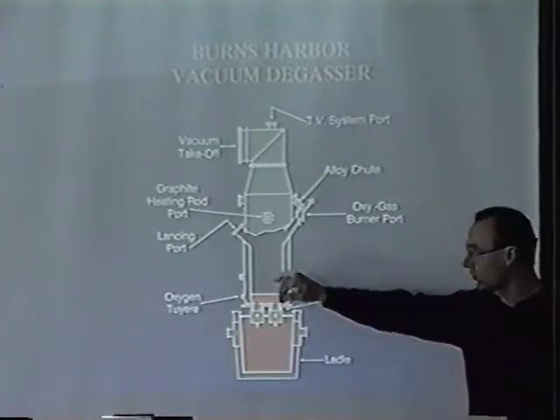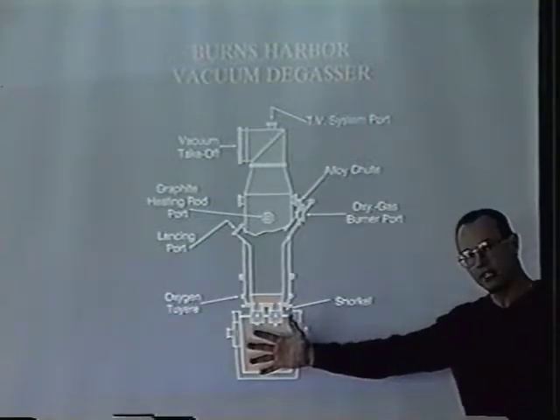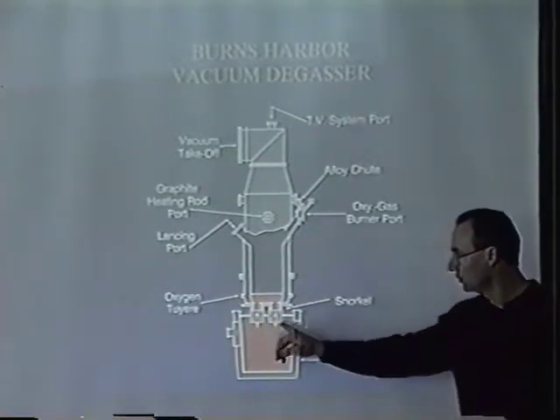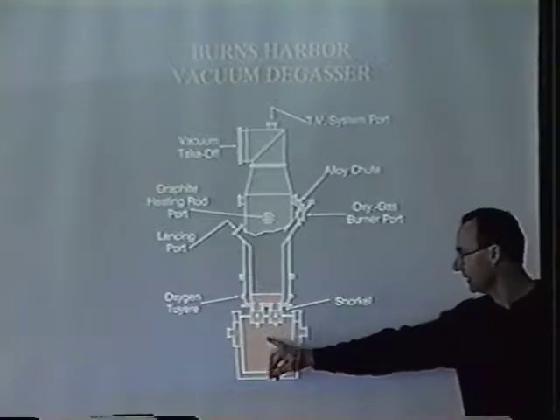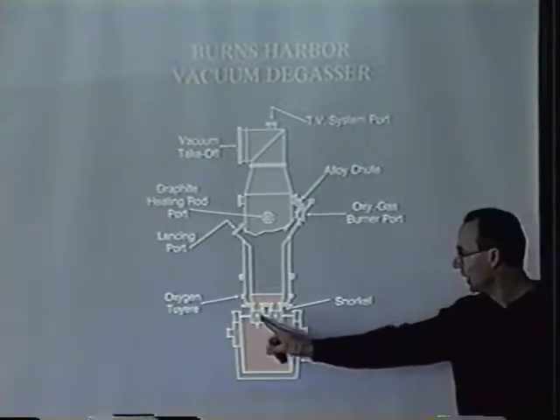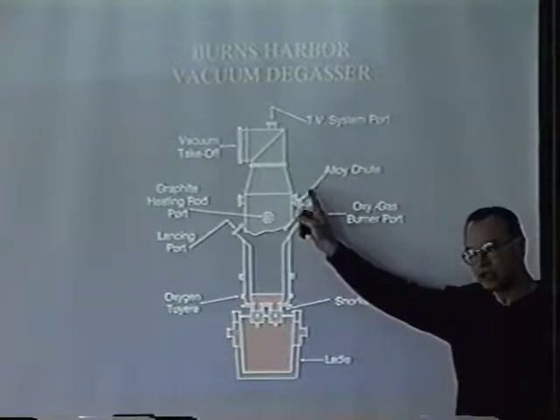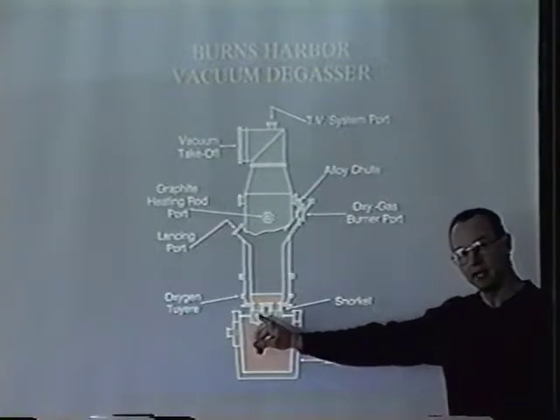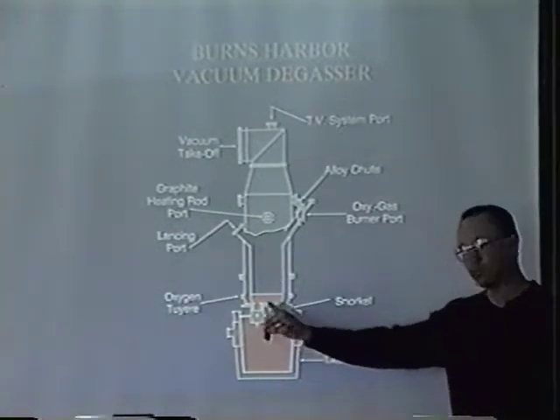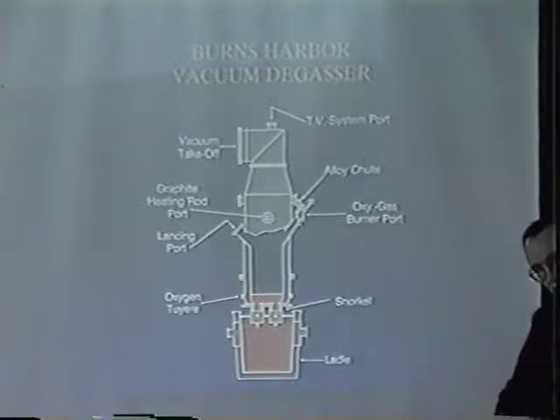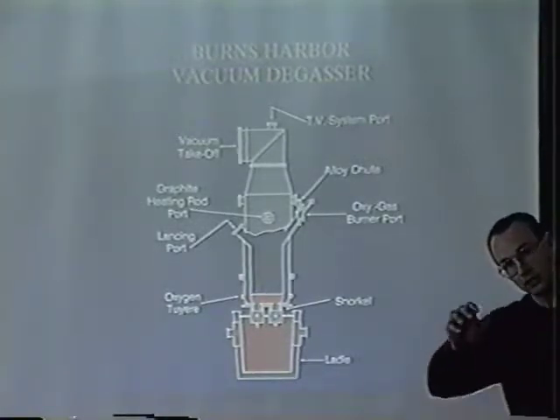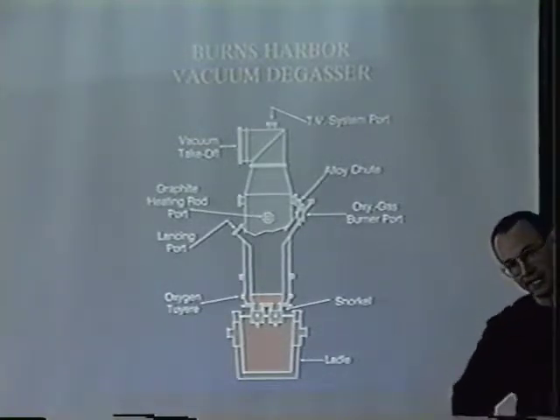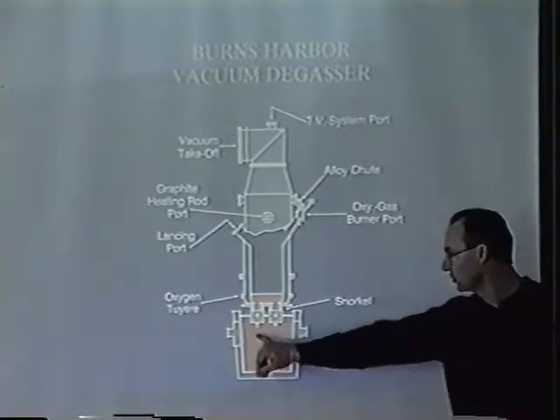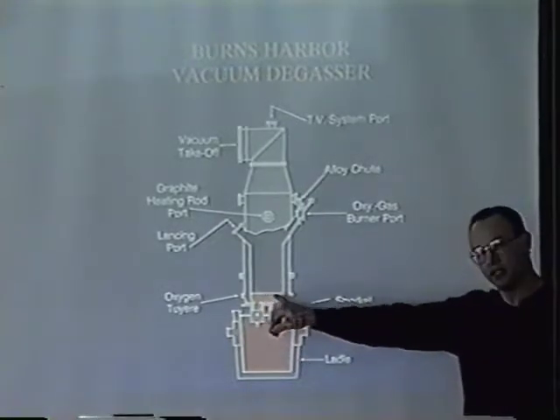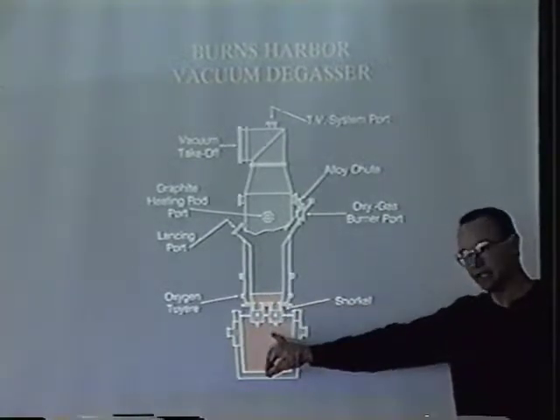It's a vacuum process. You park the ladle underneath the degasser. You drop these two snorkels down into the ladle. You turn the vacuum process on. You create a pressure difference between these two snorkels so that when you get a pressure difference, you're going to get this kind of action. It's going to want to suck up, and it's literally going to pull the steel out of the ladle up into the degasser chamber, and then it'll fall back down in the ladle.